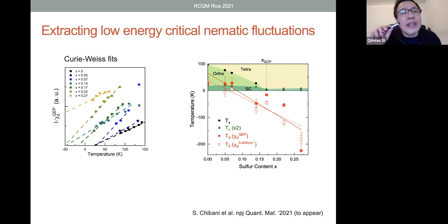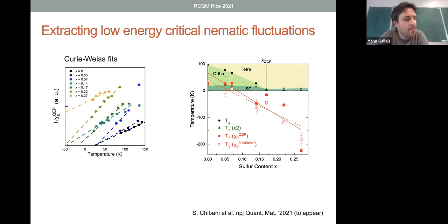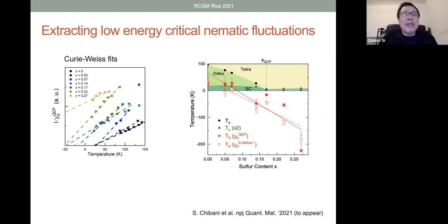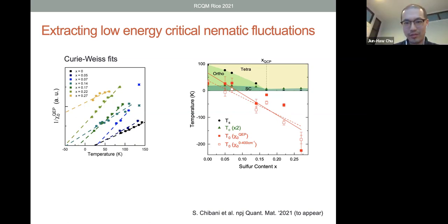Okay, I see. But the problem that we have is that the sulfur content at which T0 presumably goes to 0 has a significant TS, so that we cannot access the low temperature disordered phase. We are cut off by the structural phase transition temperature. And is that the same statement? Maybe it's a question for Zhonghao. At around 7%, do you see anything like a substantial temperature range of singular elastoresistance versus temperature? We haven't actually. Yeah, go ahead.